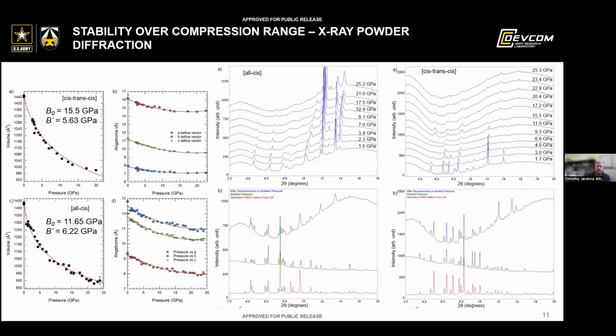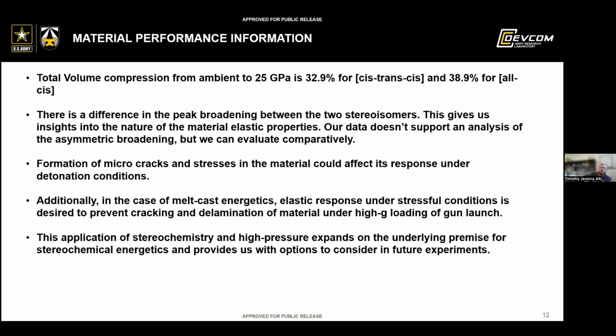Once again, we noticed that upon recovery, in comparison to the structure that was calculated from the synthesis paper, we get everything back. There's no decomposition, no issues with that. So looking at the volume compression from ambient to 25 GPa, we can see roughly 32% to 38% volume compression. That's a 6% difference. That's not a gigantic difference in volume compression, but it is significant.